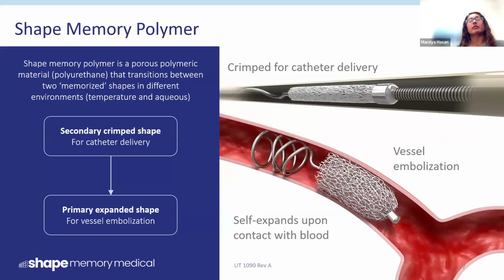Our key technology is our devices being self-expanding. We have a critical component, which is a shape memory polymer. It's a porous foam that can transition between two different shapes. We can program this material into a small geometry that can then be deployed through a catheter. From our specific device perspective, we are able to take our shape memory polymer plug and crimp it to a small cylindrical rod geometry, which can then be deployed really anywhere in the body using a catheter. Once our devices have exited the catheter and are in the vessel space, the foam component will slowly expand when it contacts blood, and it will cause embolization in whatever area it's been deployed in.